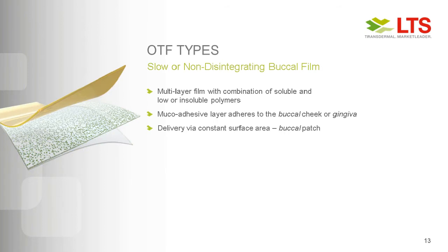The third type of an OTF are slow and non-disintegrating buccal films, or so-called buccal patches. These are usually multi-layer combinations of soluble and low or insoluble polymers. The first layer, the bottom layer, is a mucoadhesive layer, which then adheres to the buccal cheek or even the gingiva, but I think the main application of a buccal patch would be the cheek. So it has to be applied in the right direction with this mucoadhesive layer. And the second layer on top of it is really acting like a backing layer. It protects the API from being dissolved into the oral cavity. It really ensures that the API is only delivered via the surface area to the cheek, to the buccal mucosa. So it's really like a kind of a buccal patch.